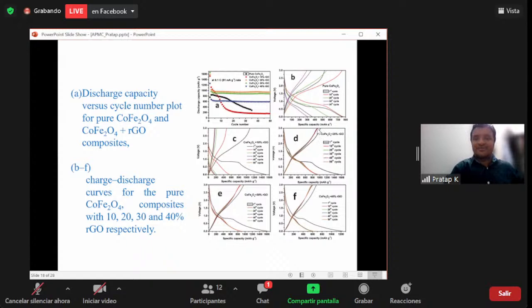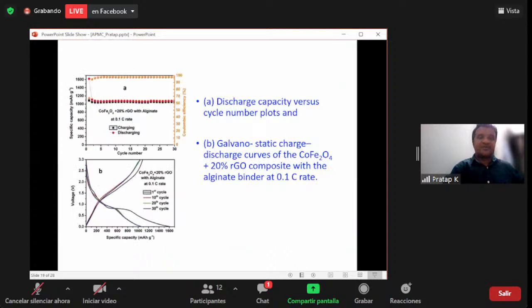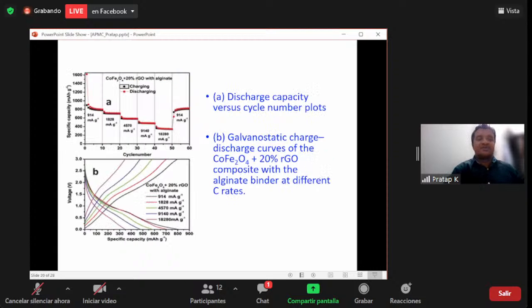So look at this cobalt ferrite with 20% RGO. They are very clear. You look at voltage, 2.5 volts, and the specific capacity is gradually this one. This is the discharge capacity versus number of cycles plot. This is cobalt ferrite with 20% RGO with alginate binder. We are checking with more cycles, and initially the capacity is around 1100, and it retained its capacity even after several charges and discharges. This is called the discharge capacity.